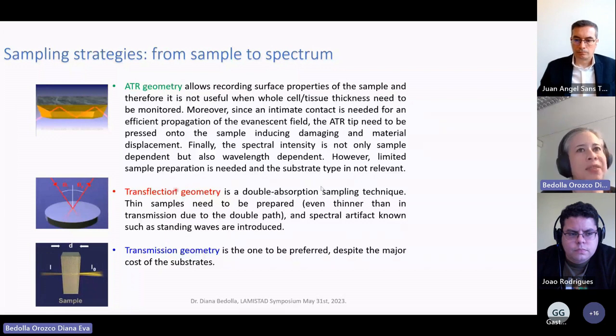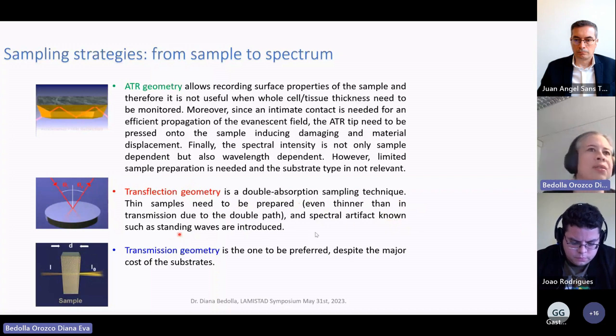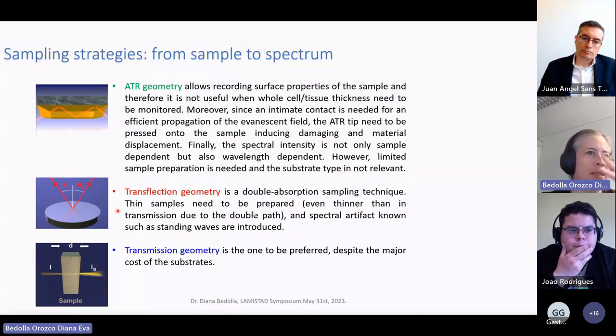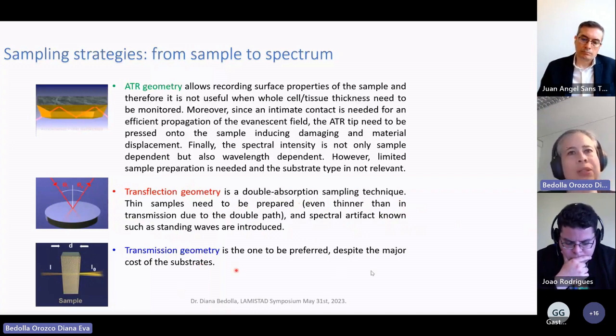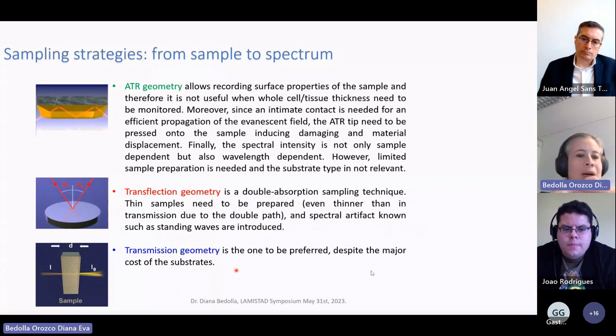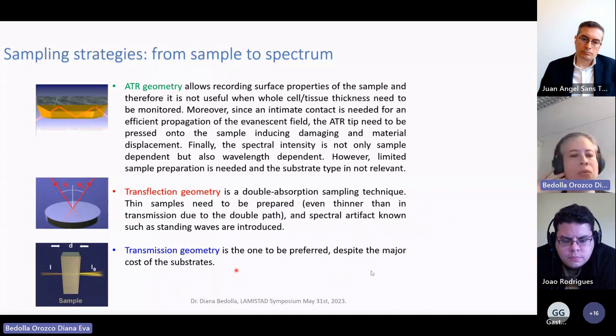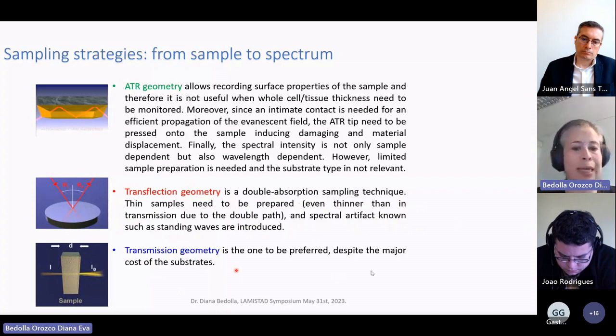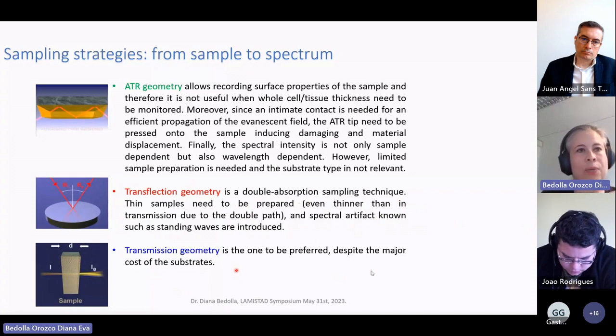You can also measure in transflection, which is a double absorption sample technique, where thin samples need to be prepared even thinner. And there is a spectral artifact known as standing waves that we have to fight there. And then there is a normal transmission geometry, which is the one preferred. And all these measurements need to be in substrates that are transparent in the mid-infrared. So that means that we don't use the usual glass that they use in biology, but we use things like the calcium fluoride windows.